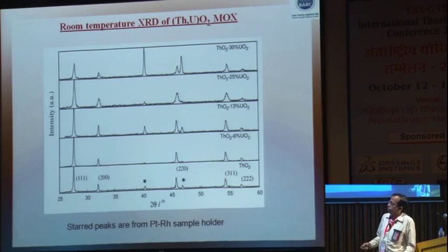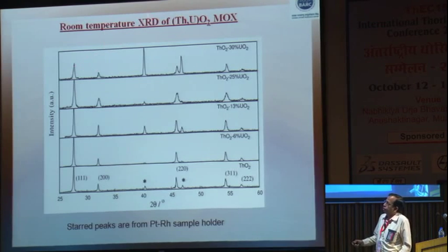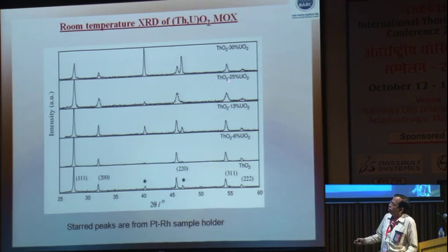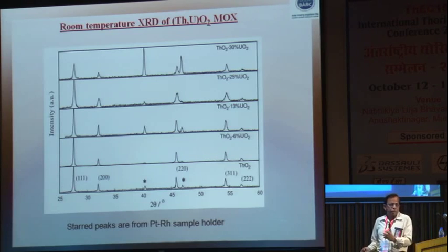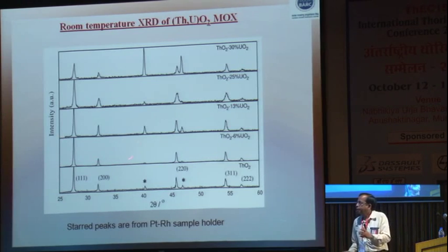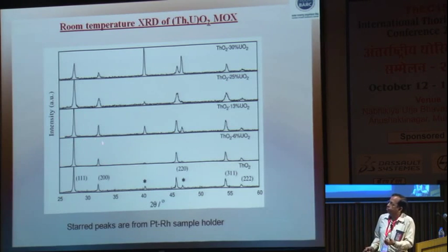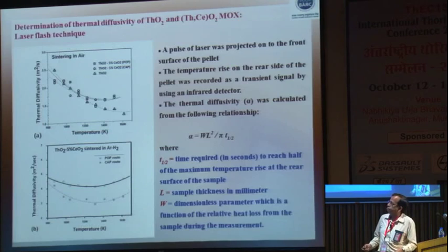We also have determined the thermal expansion by X-ray diffraction at room temperature and at high temperatures. This is a view of the X-ray diffractogram at room temperature of the different mixed oxides, and from the shift of the peak you can find out how much of the expansion has taken place, and then you can determine the thermal expansion coefficient from this kind of effort as well. So, that also has been done.